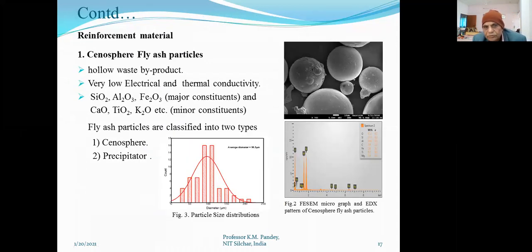Then the reinforced material, cenosphere fly ash materials. These are hollow waste byproduct, with very low electrical and thermal conductivity. SiO2, Al2O3, then Fe2O3 are the major constituents, and calcium oxide, TiO2, K2O, etc. are minor constituents. So fly ash particles are classified into two types, that is cenosphere and precipitator. Then this is the particle size distribution, and this is the FESEM micrograph and EDX pattern of cenosphere fly ash particles.